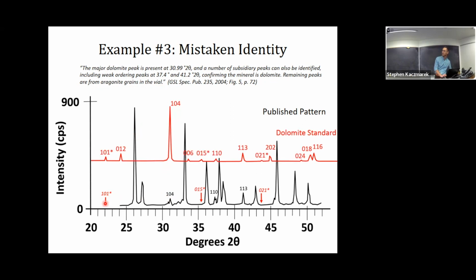Again, we can't evaluate this lower ordering peak. Here's where the 015 ordering peak should be. It's not really there. And the 021 peak's not really there.